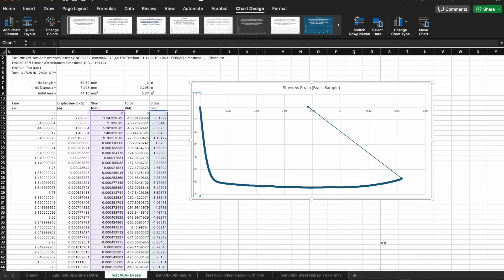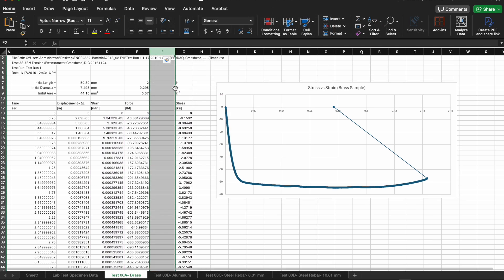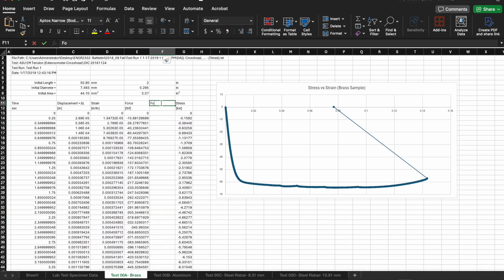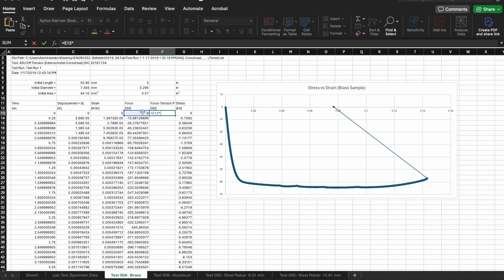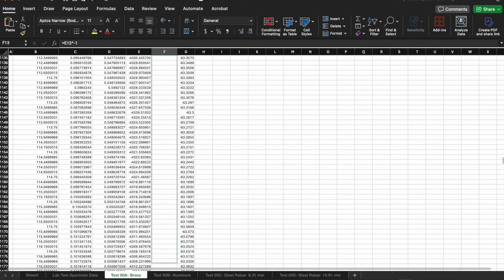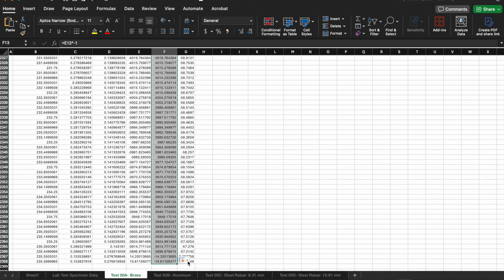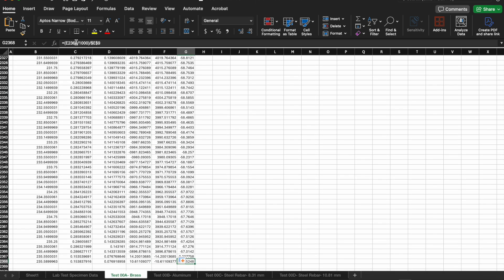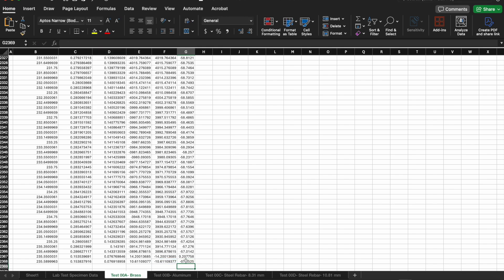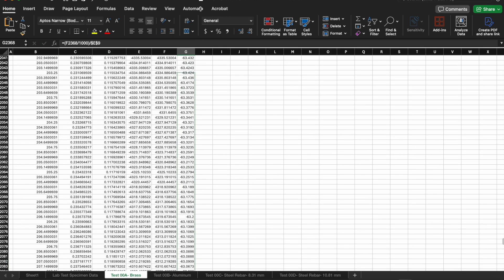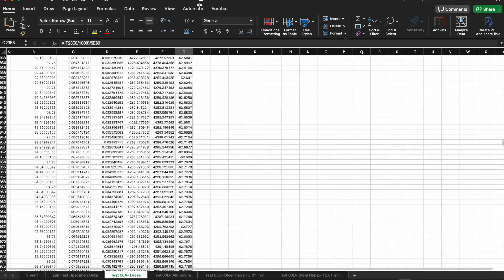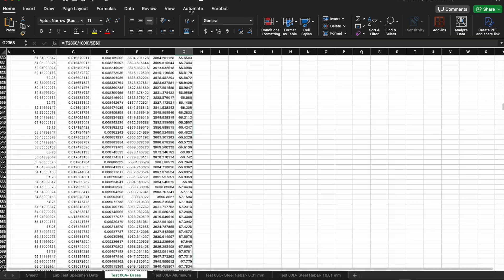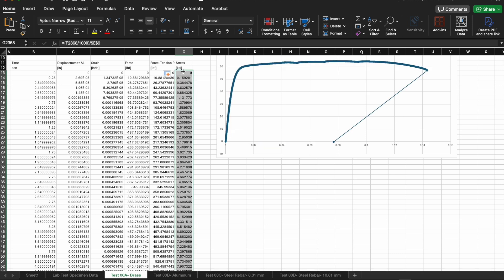If you look at the stress strain curve it's kind of mirror image or flipped upside down and this is because the UTM records tension forces as negative and compression forces as positive and so I just need to flip them around. I created another little column in here that just takes the one column E multiplies it by a negative one and now you can see the new values here in column F. Then I went ahead and updated the data to select from column F so that the plot looks more like we expect the tension in the positive XY axes for this stress strain graph.